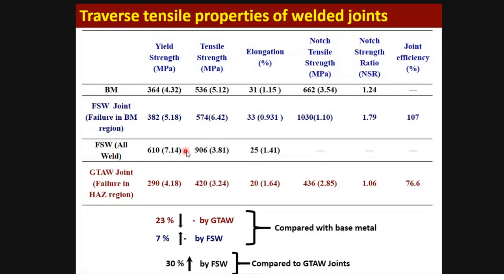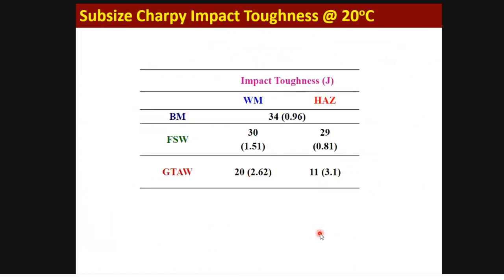And if you extract the specimen only from the weld region, you see that the strength is enormous, 906. And the GTAW joint is lower than the base material, 420 megapascal. So compared to the base metal, the GTAW joint has 23% lower strength, and the FSW has 7% higher strength. So these are the observations. And for impact toughness, FSW has given well. The weld metal is 30, base metal is 34. It's closely coming. Even in the HAZ, it is 29.